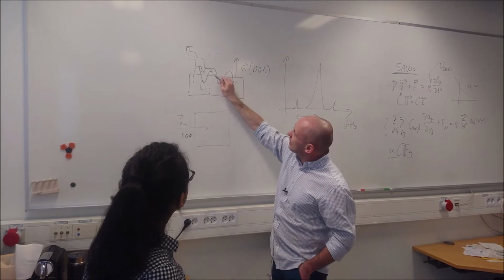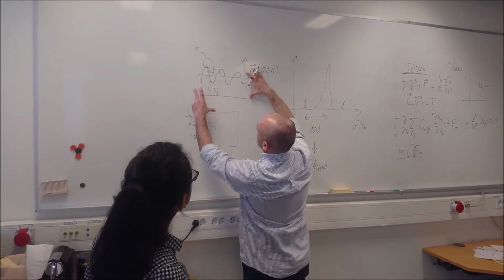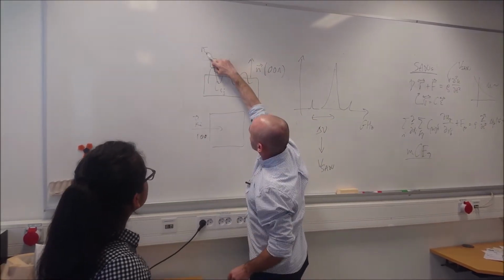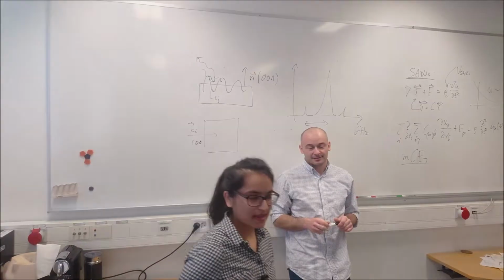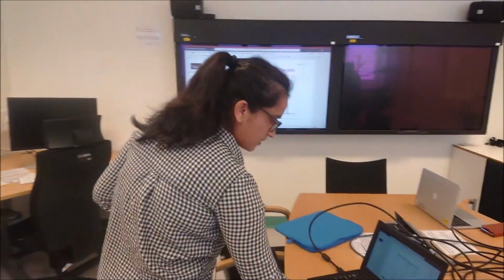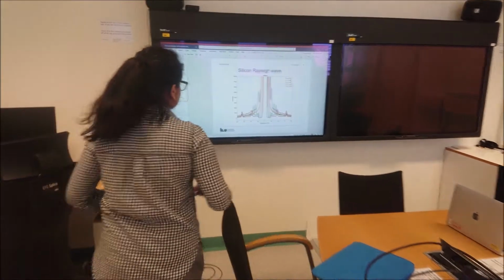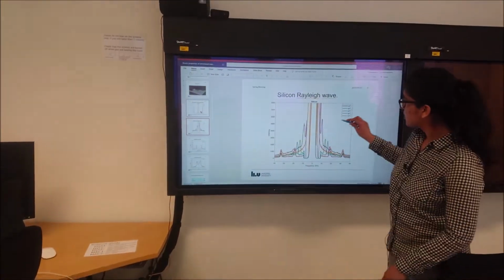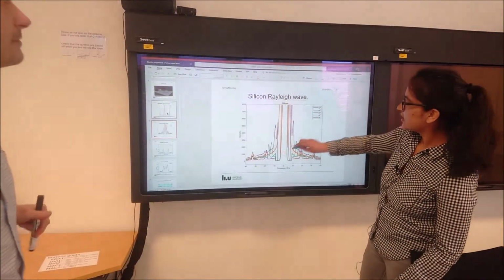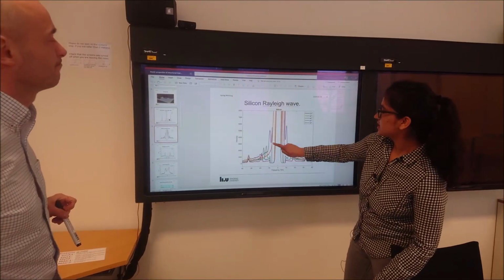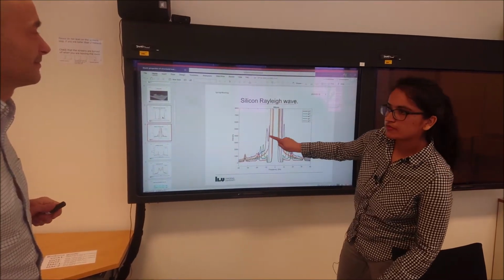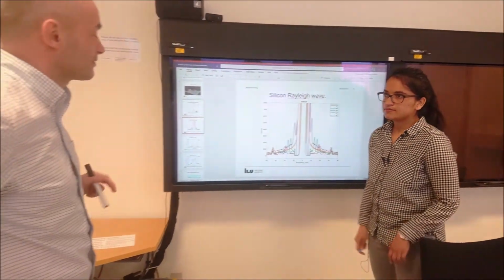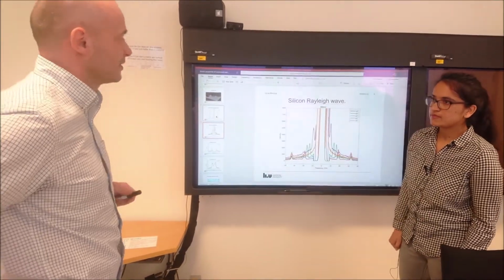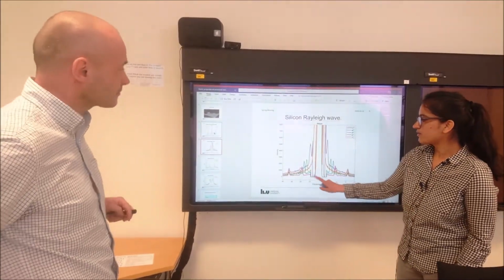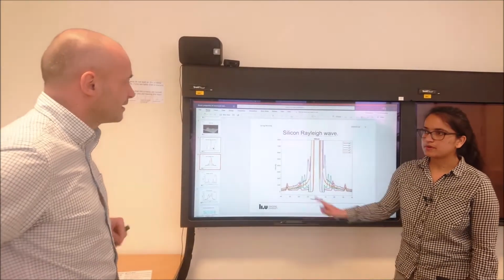Now my question is, what do you think happens if you actually change the incident angle, if your laser is coming with a different angle? Yes, actually we performed this in our lab, and here you see that for the silicon case, with the angle of incidence, the peak position is changing, and that we can confirm with our theory. Yeah, that's right. So this should be the case for a surface wave. Yes, we can relate the theoretical part and the experimental part.